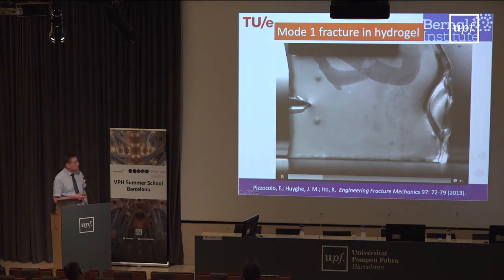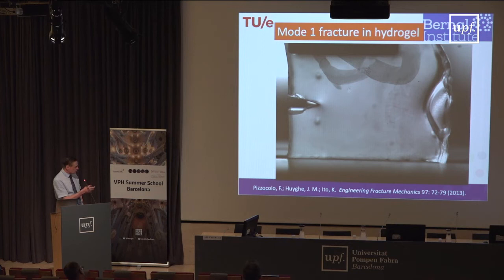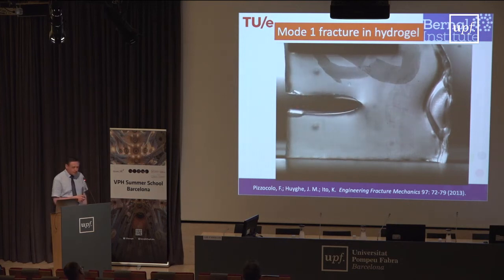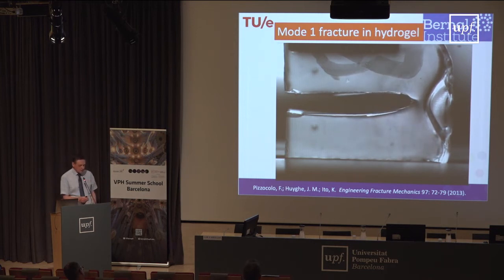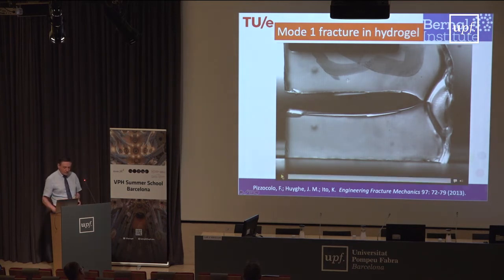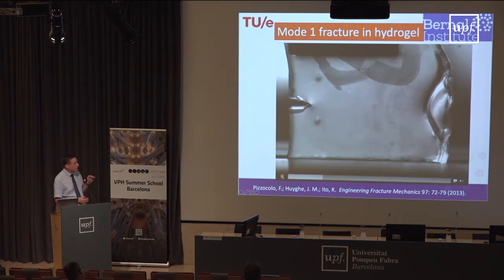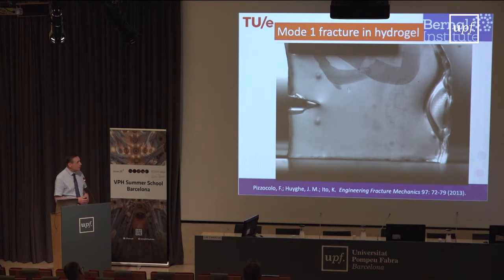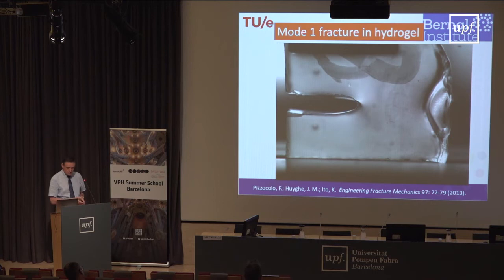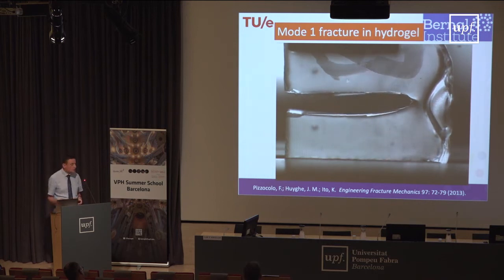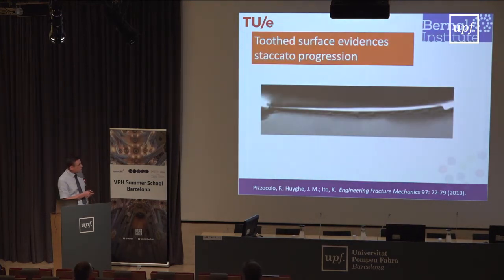And you see that it progressively propagates. And we hope it to be a one-dimensional phenomenon, but you see how it is a very complex thing happening at the crack tip, and you should think that similar things are happening in the disc and in the cartilage. But if you look very carefully, you will see that it doesn't propagate in a continuous fashion, but much more in a stepwise fashion. Suddenly it propagates, then stops, it propagates, it stops, and we find this even for a strictly homogeneous material. So gel is homogeneous. There is nothing like inhomogeneity. And if you look at the surface, you find that there are actually teeth along it, which also indicates that it is stepwise progression.